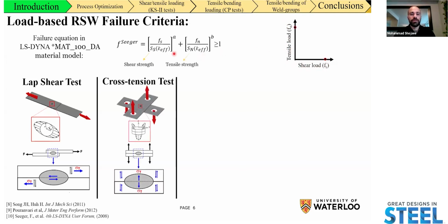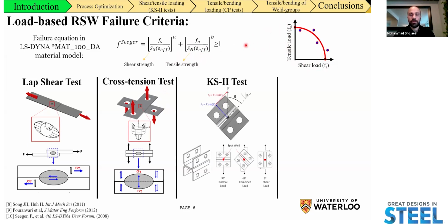The second term of this equation proposed by Seeger deals with tensile strength that is characterized by cross-tension test, and we get the tensile strength. Now, in the most basic form of this failure loci, we can fit a curve through these two data points and get our failure loci. But the issue is that we do not really have any data points at the intermediate loading conditions, and that's why the KS2 tests here come to our help, where we can perform mechanical tests at intermediate loading conditions in different ratios of shear and tensile load components, other than the two extremes characterized by lap shear and cross-tension tests.